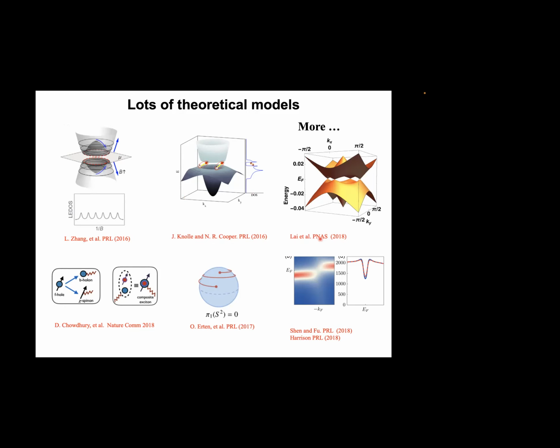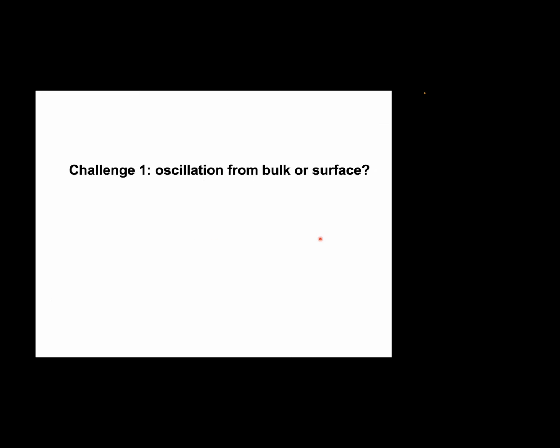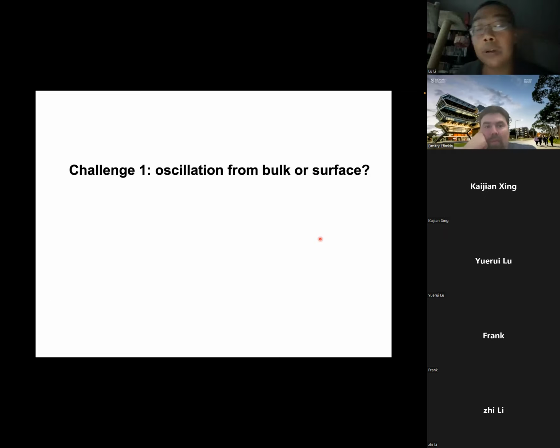As an experimentalist, I want to be quick, but I want to show how we treated the thing, right? Very first, the challenge we have to answer: are they coming from bulk or surface? As many theorists suggest, we need to do the control experiments, which means we have to have a sample. Suppose we have a sample this way. We have to cut it in half, measure again, cut to a quarter, measure again, and see if the oscillation amplitude scales with that vanishing volume. That project went nowhere, because we can never consistently get back to the strong magnetic fields without any change of conditions in each run.